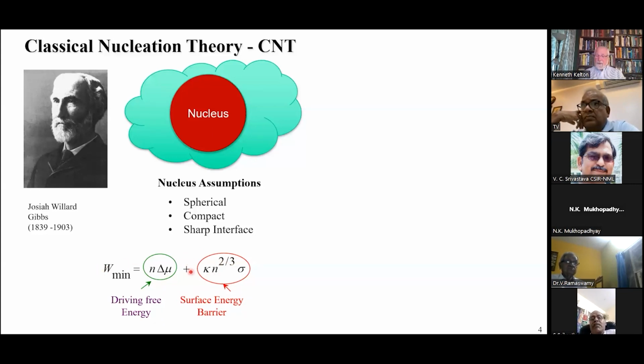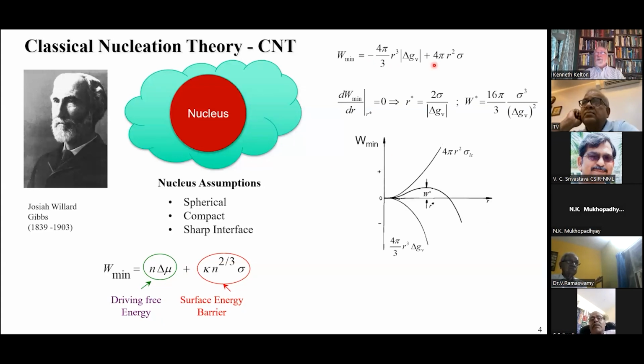Now, this is written in terms of N, but we often see it written in terms of the cluster size. What I've done now is explicitly introduce the fact that delta mu is negative by taking the absolute value of delta GV and introducing a negative sign. So this term is negative and this term is positive. This term dominates for large cluster sizes, and this term dominates for small cluster sizes. That means there has to be a maximum in the work of cluster formation, and we all know about that. You take the derivative, you find a quantity called the critical size for nucleation by setting the derivative equal to 0, and from there you can reconstruct the work of cluster formation for a critical cluster.